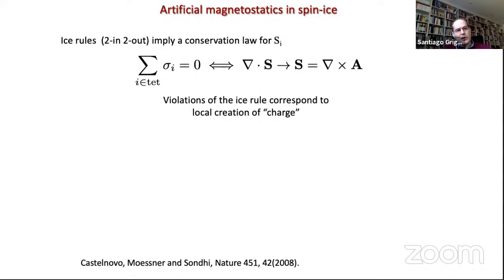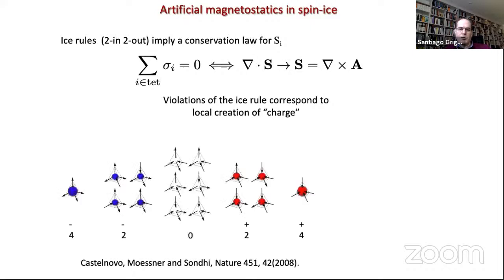And now you can use a sort of a different language. You can think that your ground state comes from a system which has no charges corresponding to the field, and excitations would correspond to local creation of charges, right? So once I violate this divergence-free condition, I'm going to get charges. And what you see is that because here you have Ising spins, you get these two flavors, only two flavors of charges.